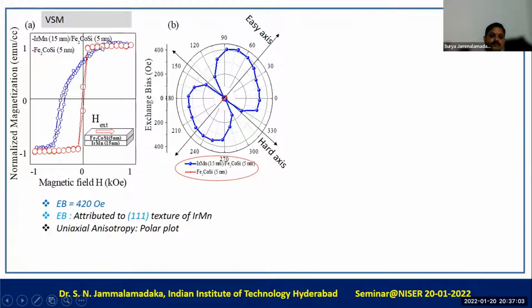the magnetization loop. But please remember that we didn't do any field cooling over here. Without field cooling, immediately in the as-deposited film, we could see a shift of the magnetization loop. Okay, so this shift we have calculated, and this exchange bias value is found to be 420 Oersteds.